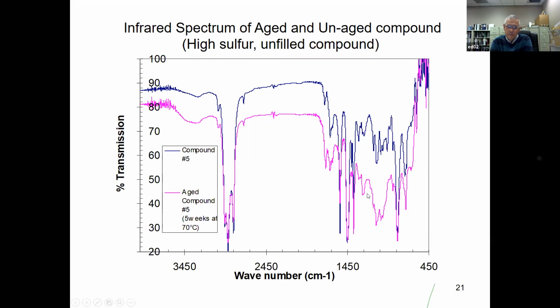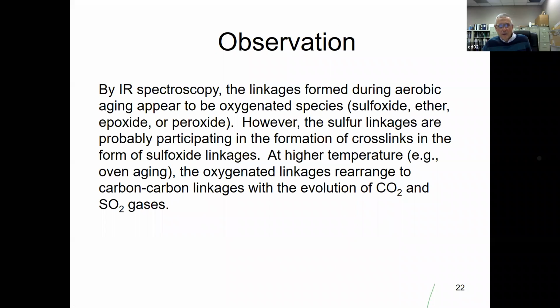So that is as far as we were able to go on that subject. We say by IR spectroscopy, the linkages formed during aerobic aging appear to be oxygenated species: sulfoxide, ether, epoxide, or peroxide. However, the sulfur linkages are probably participating in the formation of crosslinks in the form of sulfoxide. So my best guess is that the newly formed linkages are sulfoxide. At higher, oven aging temperatures, presumably the oxygenated linkages rearrange to carbon-carbon linkages with the evolution of CO2 and SO2 gases.